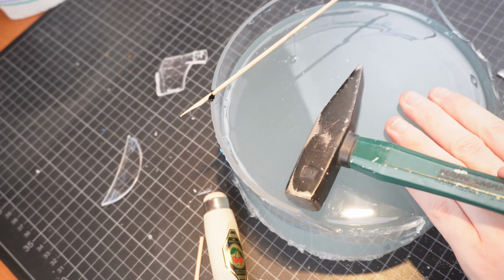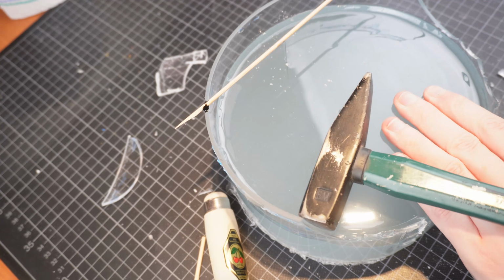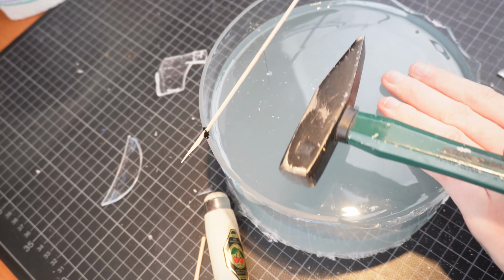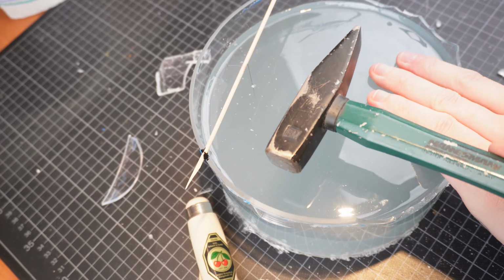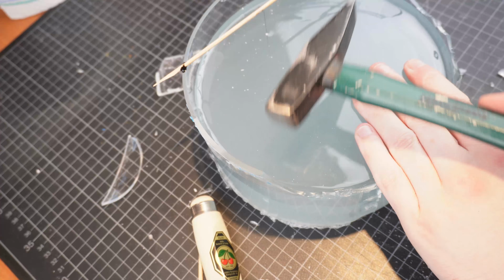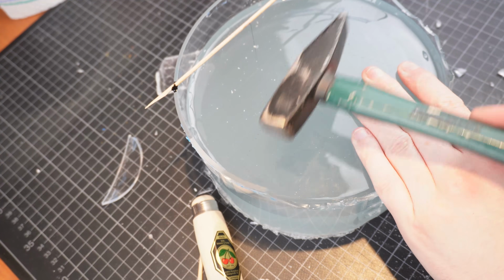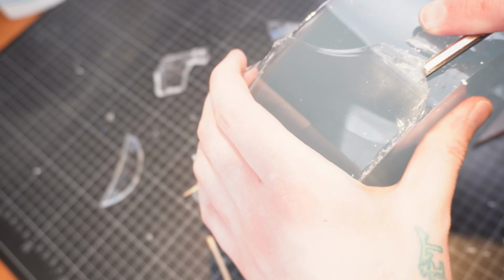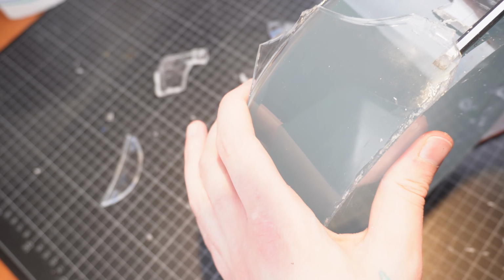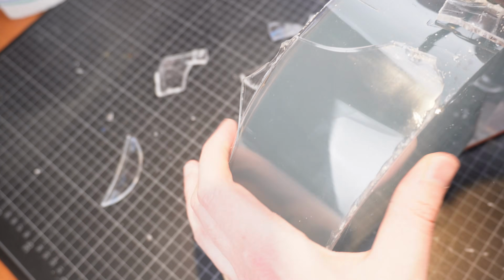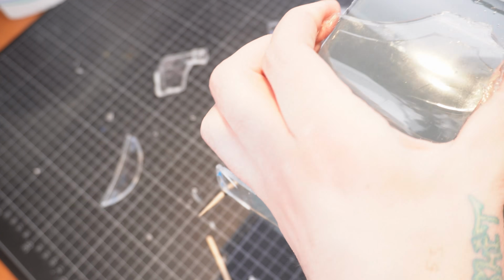My initial idea was to break away the bottom plate, then use a saw to cut a groove into the acrylic tubing, and then use a hammer to break the acrylic tubing away. But oh boy, was I wrong. This didn't work that great, and I had to use a chisel to break the acrylic tubing off the epoxy block. And as you can see, brute force isn't the best idea when working with epoxy resin, so of course I did some heavy damage to the epoxy block.